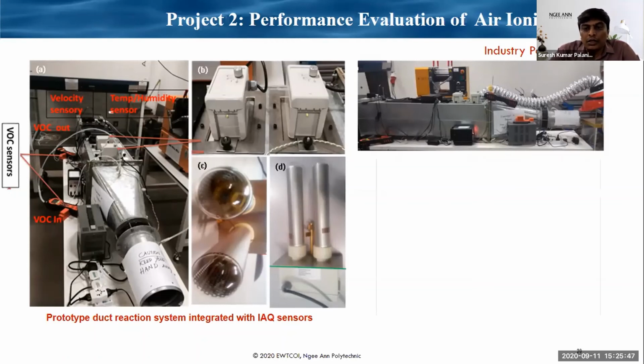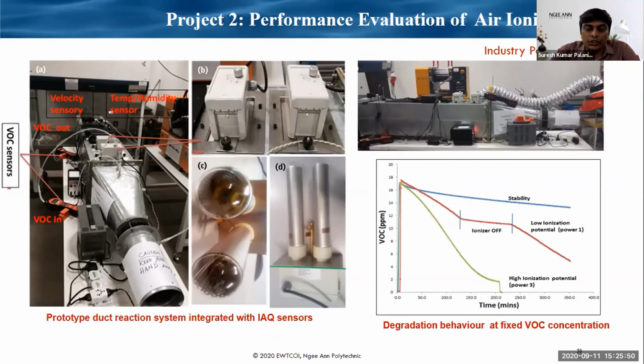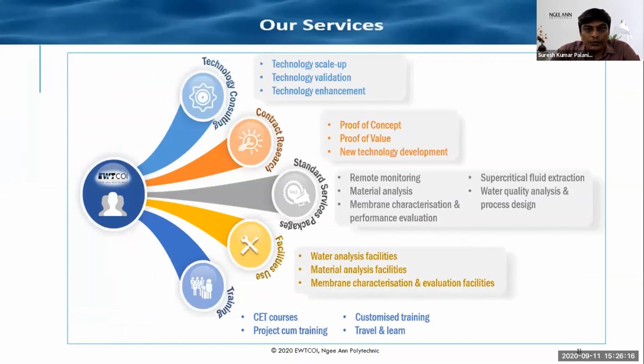and we measured the degradation performance with particulates and then VOCs. Our initial findings show these VOCs with this ionizer have good performance, good degradation with respect to time. And then this client has implemented this ionizer at sites where there is a high concentration of particulates and VOCs. We also studied this ionizer for ozone measurement, which it can emit at the standard limit of 0.05 ppm per hour.